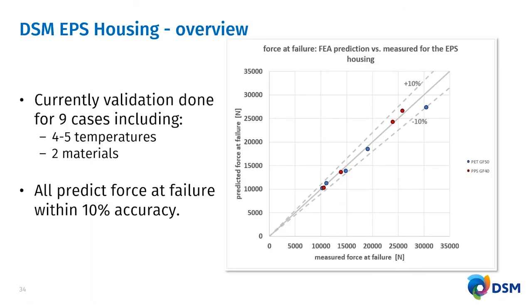All right, so here's an overview of the results. Some additional results. We are comparing the predicted force at failure with the measured force at failure in newtons, and as you can see here, there's a fair amount of a good agreement between the two. What we have here represented in the blue dots are a PET with 50% glass and the PPS with 40% glass represented with the red dots. And these are basically 9 different cases, including 4 to 5 temperatures. And they all fall within this basically this window of meeting our goal for 10% accuracy. So that's good.